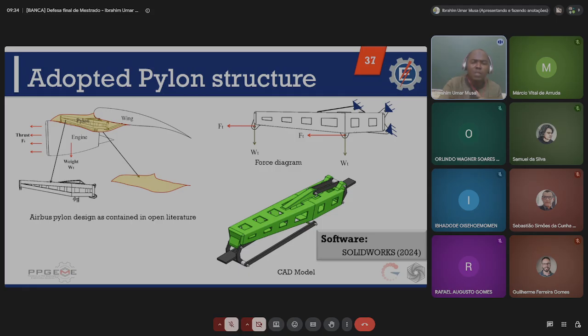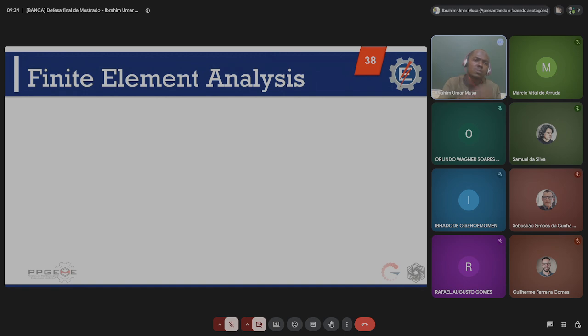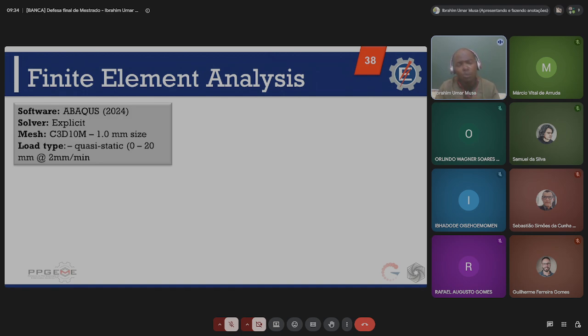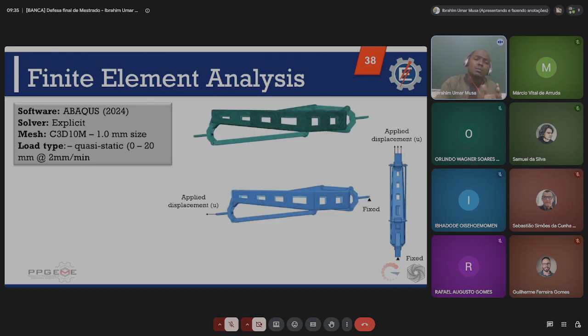So based on this, we developed our model using SolidWorks 2024, and we imported it into an Abaqus 2024 model using the explicit solver and a C3D10M mesh of size 1 millimeter, applying a quasi-static load from 0 to 20 millimeter displacement at 2 millimeter per minute speed. We have these images showing the mesh as applied and how the structure was clamped and loaded.